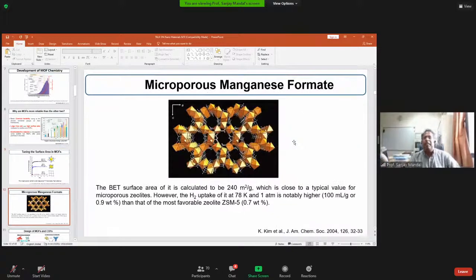Now, many people think that you need some exotic material. But look here, microporous manganese formate. You know, manganese formate is a very well-known compound, and it has a surface area of 240 meters squared per gram, which is close to microporous zeolite. And its H2 uptake is even higher than that of ZSM-5, which is a very well-known zeolite. So you don't have to look around for what to do. You have to know what you need to do.